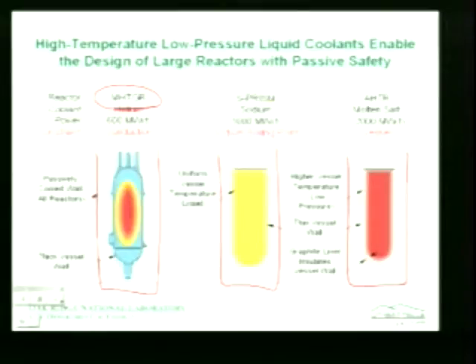But if you look at it, the hot point in the reactor is in the middle of the reactor. To get the decay heat out, you have to move the heat from the center of the vessel to the vessel wall by conduction through 15 feet of graphite. Well, graphite's an okay conductor, but not that good. As a consequence, it takes almost 1,000 C in temperature to move that decay heat this distance to the wall. And then, of course, you have to move it from the wall through the cooling jacket to the outer environment. But the large temperature difference needed to make the system work means that you're limited to a power level of about 600 megawatts electric. It's a conduction heat limited system.